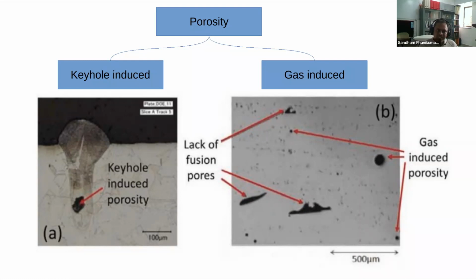And if the vapor column doesn't move in a steady manner through the powder bed, then what happens is that some of that will be left behind without a closure of the void, and then you start seeing the keyhole induced porosity. Which means that it is a problem caused because your laser heat intensity is slightly on the higher side. Typically, if you increase the diameter of the laser beam, this problem will go away. Okay, so if you have a problem with keyhole porosity, if you increase the diameter of the laser beam, then this problem will go away because it will prevent the formation of keyhole basically.